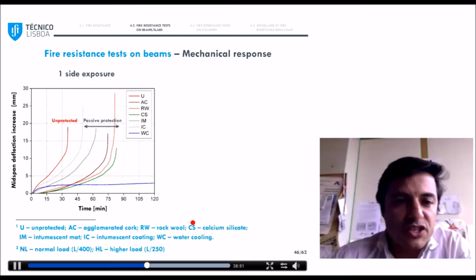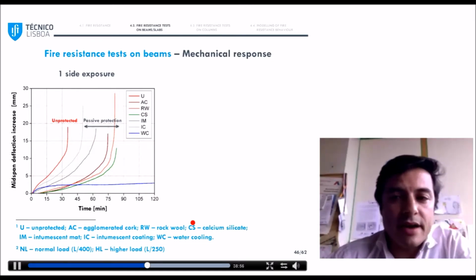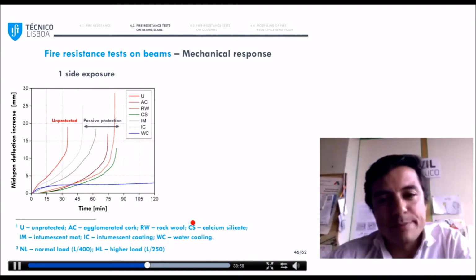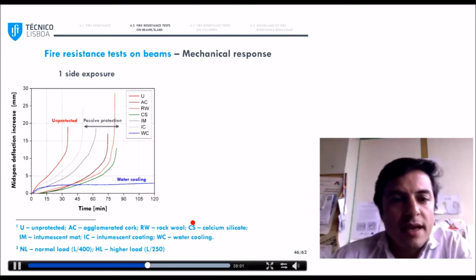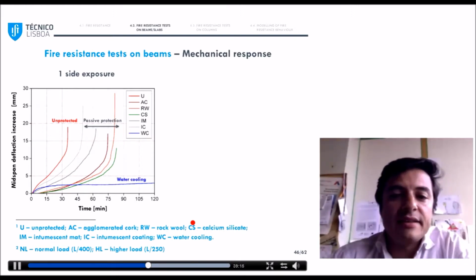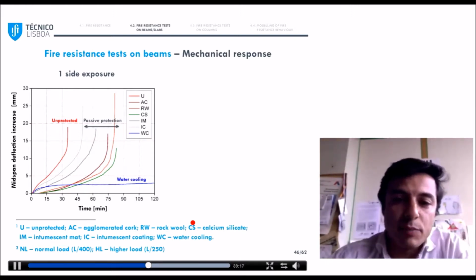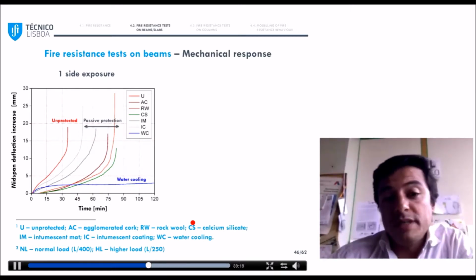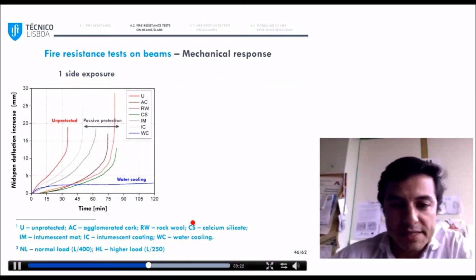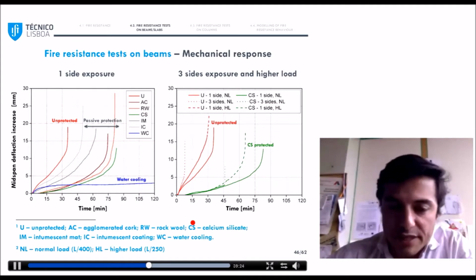Next, for the passive protections, you can see that they had an effect in slowing down the deformation increase, especially for the thicker protections. And for the water cooling, this blue curve, you can see that it followed pretty much the temperature. So there was an initial increase due to the loss of stiffness of the bottom flange and the heating. And then the deformations almost stabilized at some point, indicating the efficacy of this system for this type of exposure.